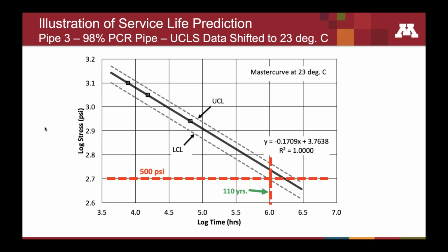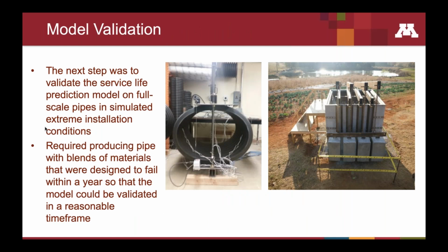The question was, though, right now we just have a model as to how long these pipes manufactured with different percentages of recycled materials would last. What we really wanted to do was evaluate and test that model. And one way to test that would be to install a pipe so that the stress was 500 psi on it and wait around for 110 years and see if we had failures. That didn't seem to be too attractive of an alternative, particularly for somebody like me that was trying to finish my PhD dissertation in a timely manner. So we needed to accelerate the test in order to validate, and we did this by two ways.